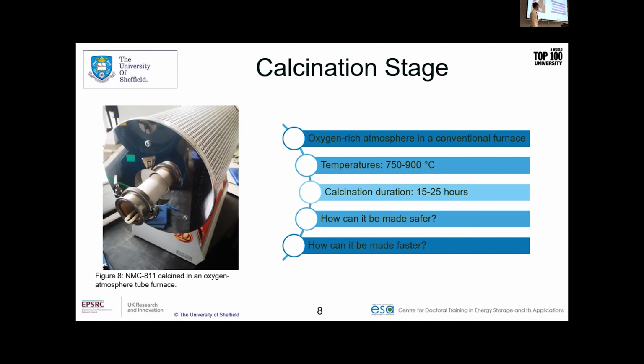But yeah, we like to calcine it in this sort of conditions for about 15 to 25 hours, depending on the precise regime that they're going for. And depending on the ratio of the nickel, depends on the temperature. So lower nickel proportions is a little bit more stable because of the increased cobalt and manganese stabilizing agents. So you can have a higher temperature in order to calcine and make the final product. Whereas the higher the nickel ratio, the more unstable the nickel ions are, and therefore you need to keep it at a low temperature to monitor and moderate the evolution of the nickel cations.